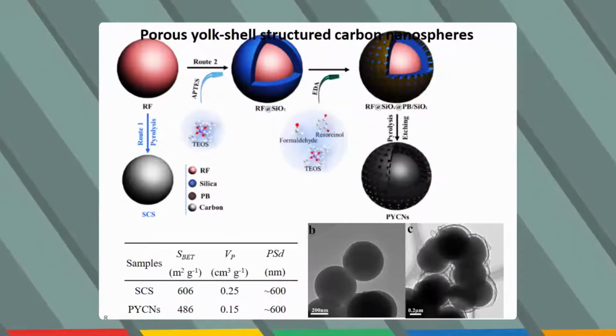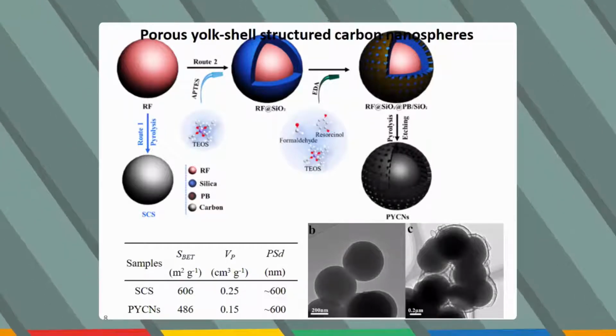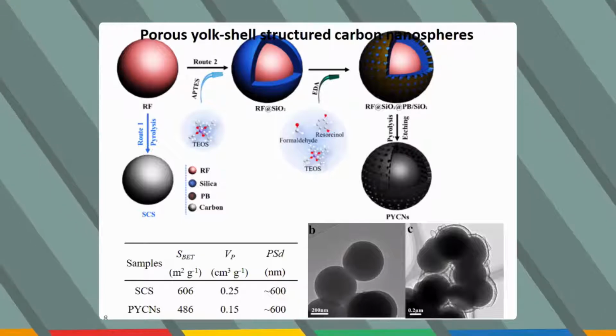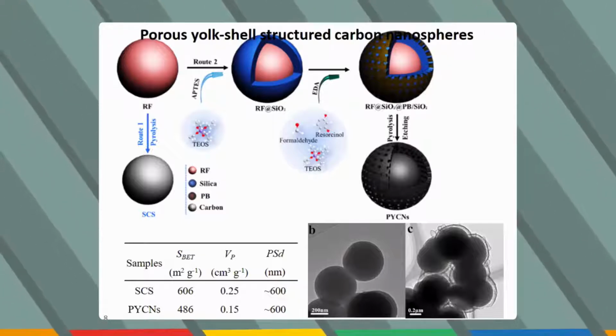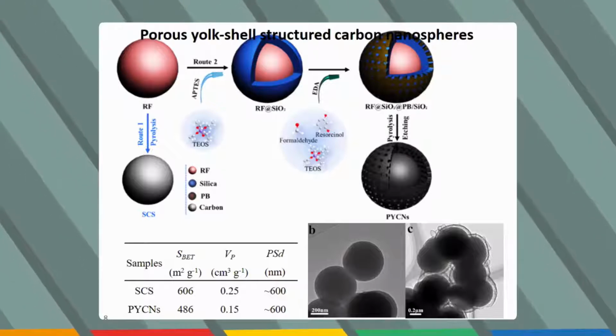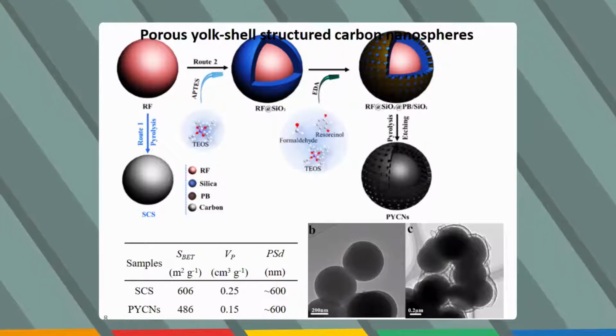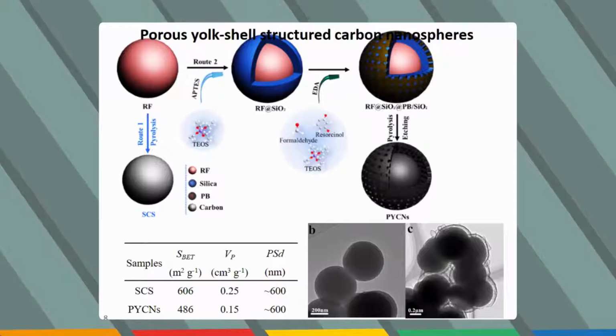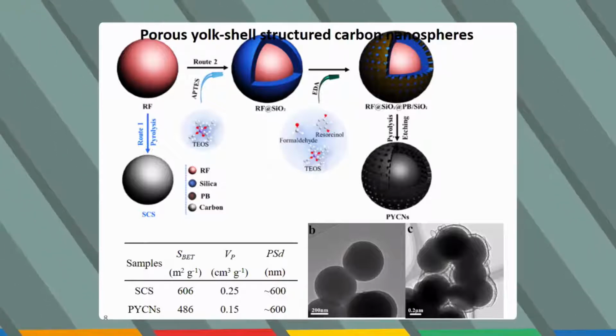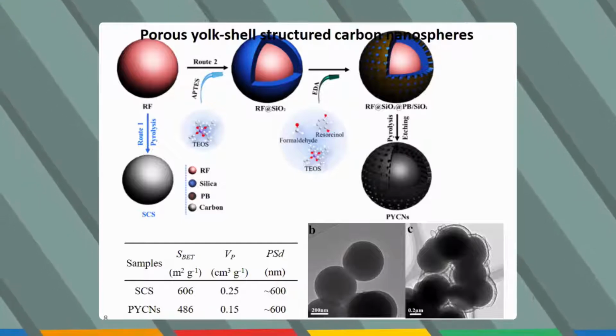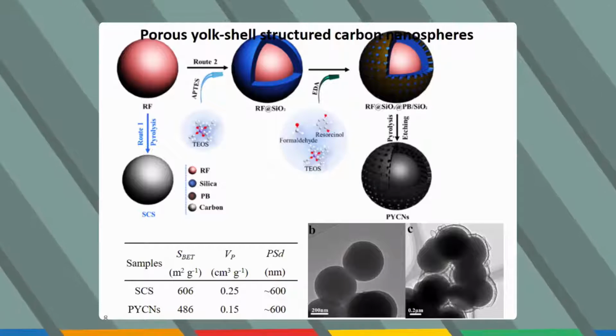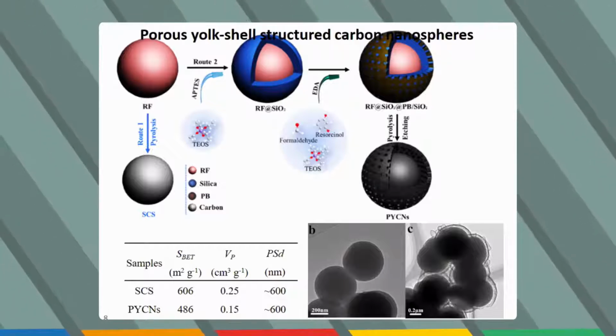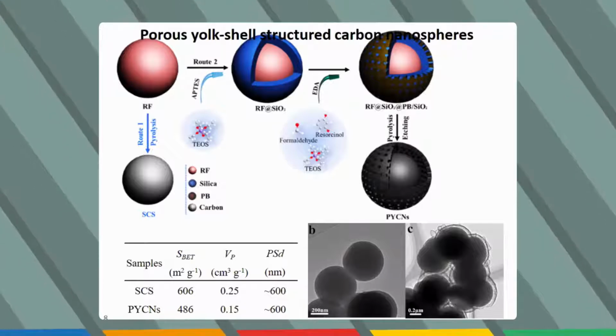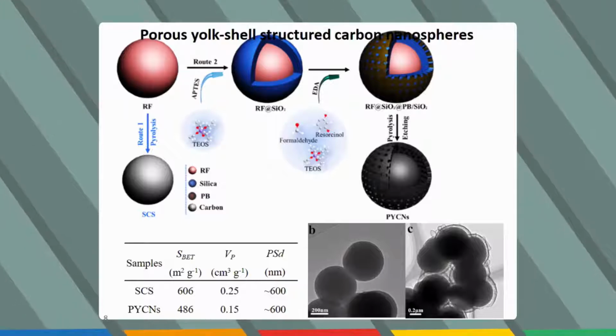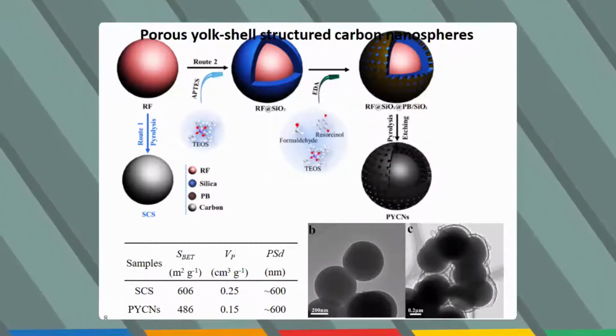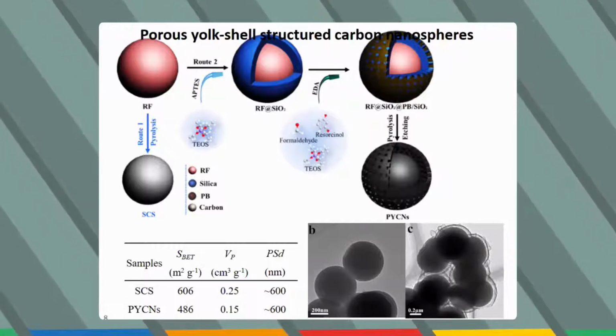Another type of carbon spheres that we prepared was the porous yolk shell structured carbon nanospheres. In this method, we took the resorcinol formaldehyde resin and calcined it straight to 700 degrees Celsius to form the solid carbon spheres. In another route, we coated the resorcinol formaldehyde spheres with silica, followed by ethylenediamine to form the pores, and finally calcining at 700 degrees Celsius. The TEM images are shown at the bottom, as well as the table for physicochemical properties.